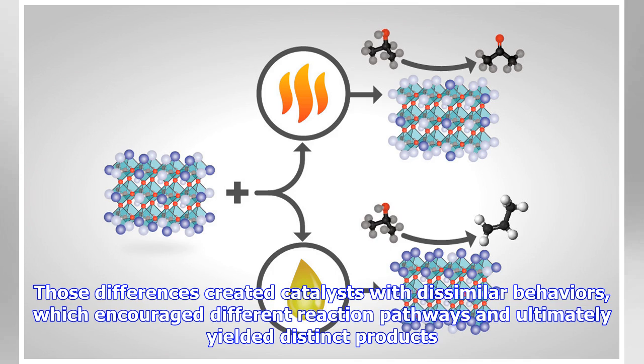For some crystalline catalysts, what you see on the surface is not always what you get in the bulk, according to two studies led by the Department of Energy's Oak Ridge National Laboratory. The investigators discovered that treating a complex oxide crystal with either heat or chemicals caused different atoms to segregate on the surface, i.e., surface reconstruction. Those differences created catalysts with dissimilar behaviors, which encouraged different reaction pathways and ultimately yielded distinct products.